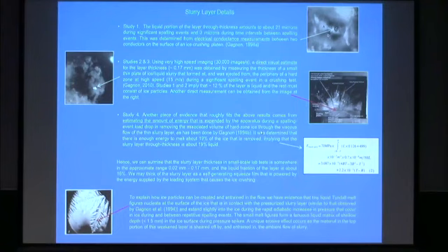In addition to that, you can make some simple calculations just determining the amount of hard zone material that's removed during a spalling event just from your compliances and instrument measurements, and you know the amount of energy that went into that from your system, and you can determine how much melt was produced.